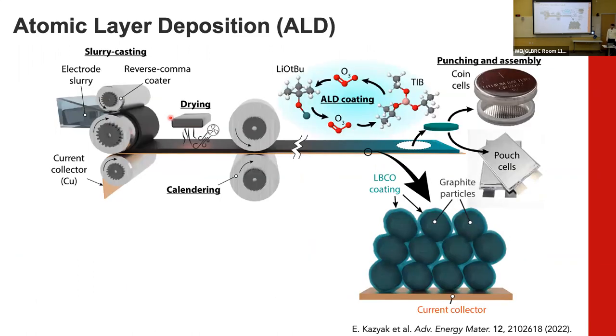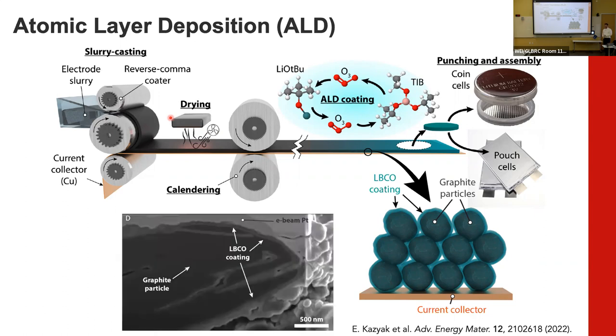To coat the electrodes, everything up until the coating process was the same. We coated the paint on the slurry, we dried it, then we densified it, we cut out these electrode sheets, and then we did what's called atomic layer deposition, or ALD. I'm not gonna go into detail here, but it's a gas phase process. It uses self-limiting half reactions at the surface so that it's not a line of sight process. And we can conformally coat all the way down into the nooks and crannies of this porous electrode.